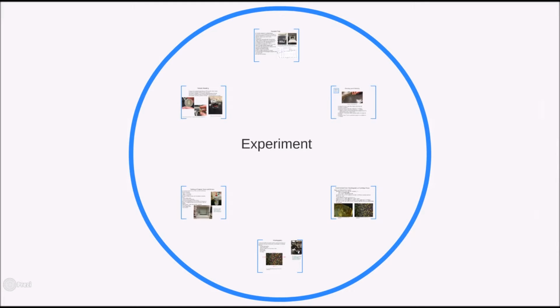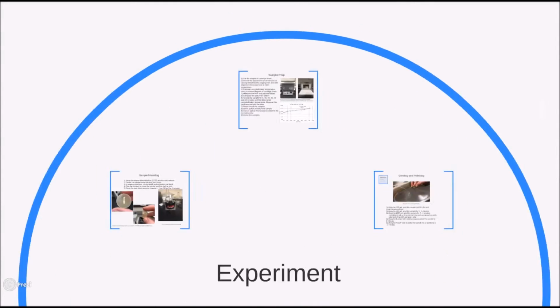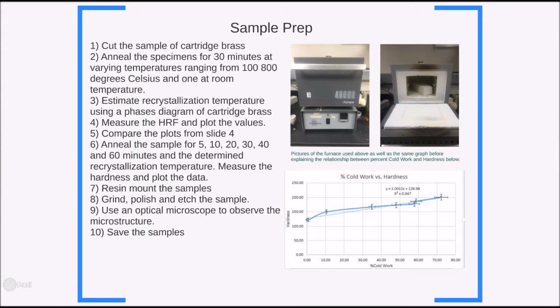The procedure is as follows. Cut the sample of cartridge brass into desired sample sizes. Anneal the specimen for 30 minutes at varying temperatures ranging from 100 degrees Celsius to 800 degrees Celsius, and an addition of 1 at room temperature. Using a phase diagram of cartridge brass, estimate the recrystallization temperature, measure the HRF, and plot the values. The recrystallization temperature can be determined from this plot.